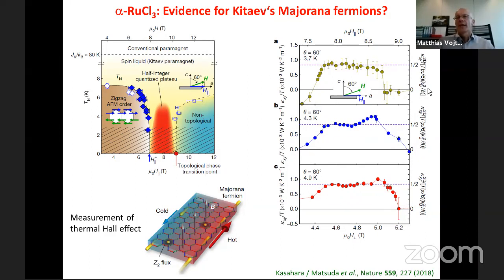What is important on the experimental front is to follow this signal to low temperatures. You see this ends at 3.7 Kelvin for a reason which Matsuda is saying: his cryostat can't go lower, which, since this is a really important problem, is not a good excuse. So one must follow this result to low temperatures. And again, theory predicts that you lose quantization in a very specific way. And this must be verified experimentally. And then we see what this is.